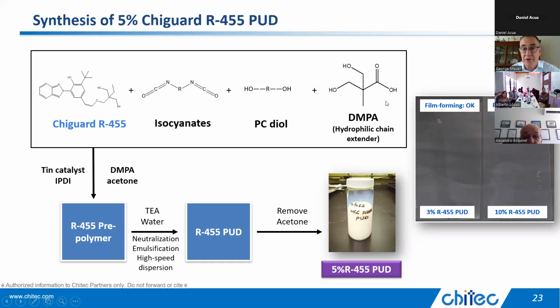There's a lot of amines you can use that will neutralize this in order to make the salt that allows you to make a very stable dispersion. In this case, they're using, I guess it's triethylamine. You need to disperse it in, so high-speed dispersion in order to make the particles the most consistent particle size.